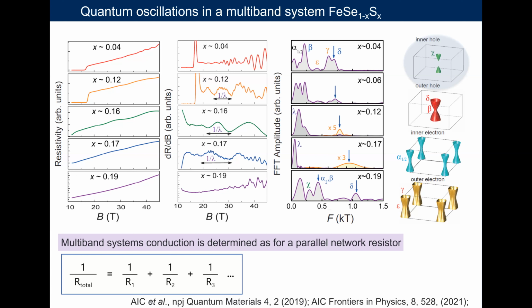ARPES told us that there is a small 3-dimensional pocket which will show up as we add sulfur substitution. So one potential reason is because of this particular pocket. Being a smaller pocket with larger mobility, it could dominate the resistivity in a multi-band model, assuming that this behaves like a parallel metal resistor.